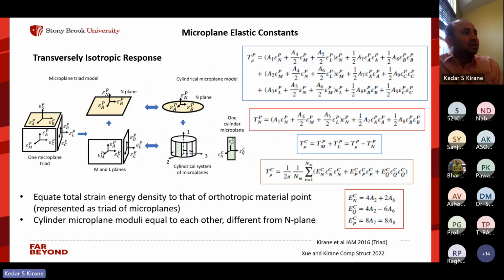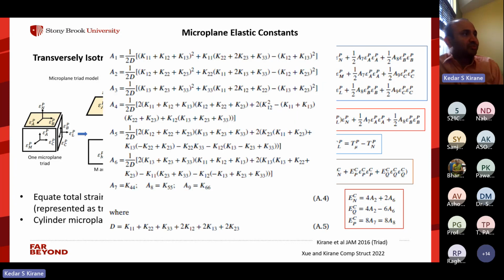Okay. So this is the framework of the cylindrical microplane model, where, instead of a sphere taken for concrete, for composite you take a cylinder and then you project a strain tensor onto these cylindrical microplanes, obtain the stress vectors, and then calculate the strain energy density. And using that, you can calculate the stiffness tensor to get back the stress tensor. Okay, so that is the overall approach.